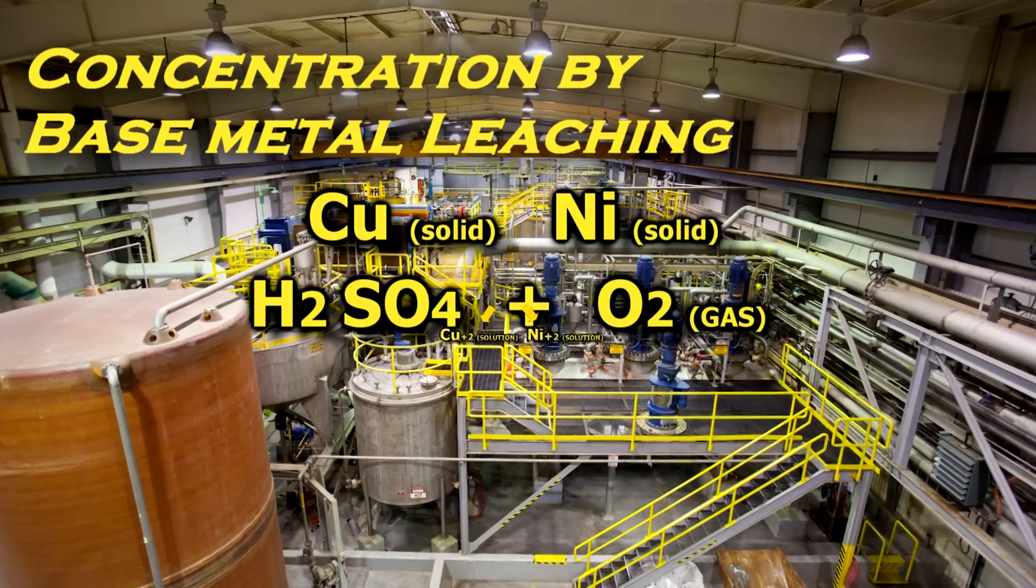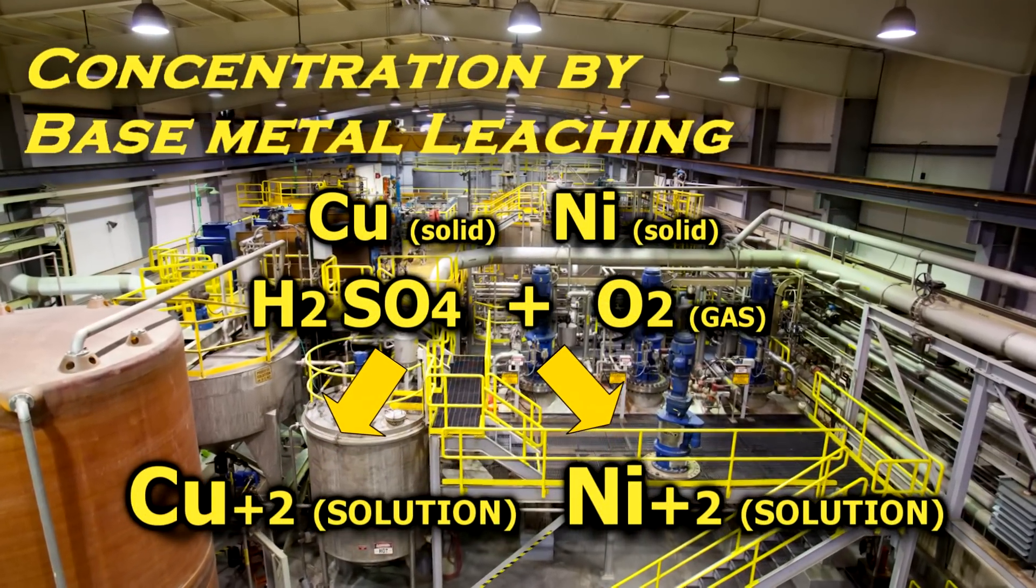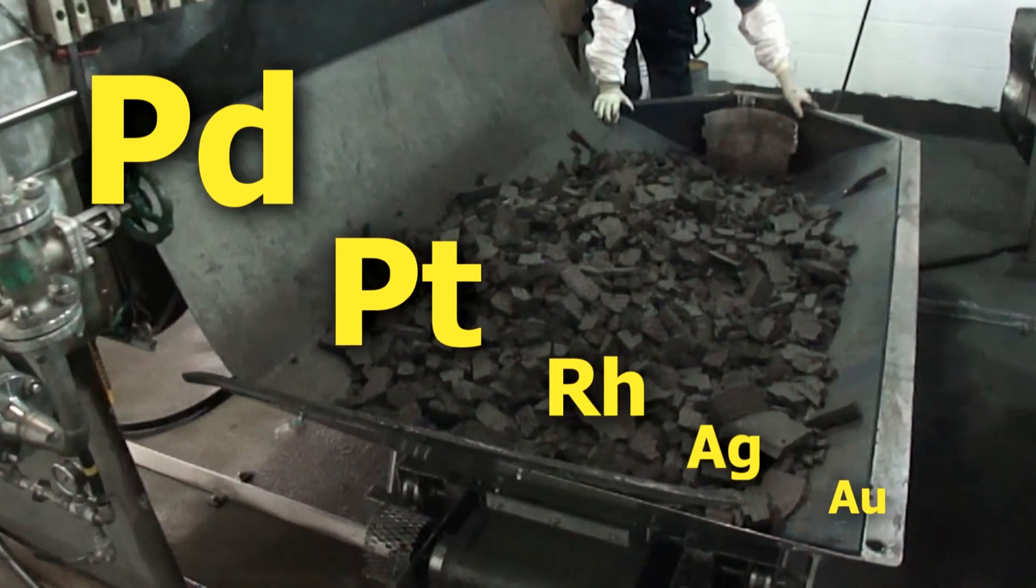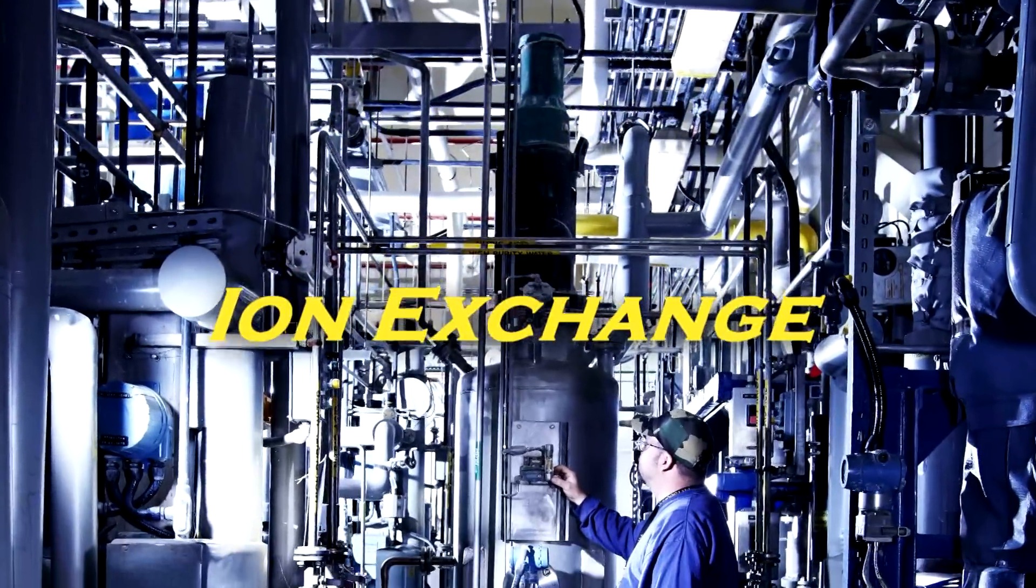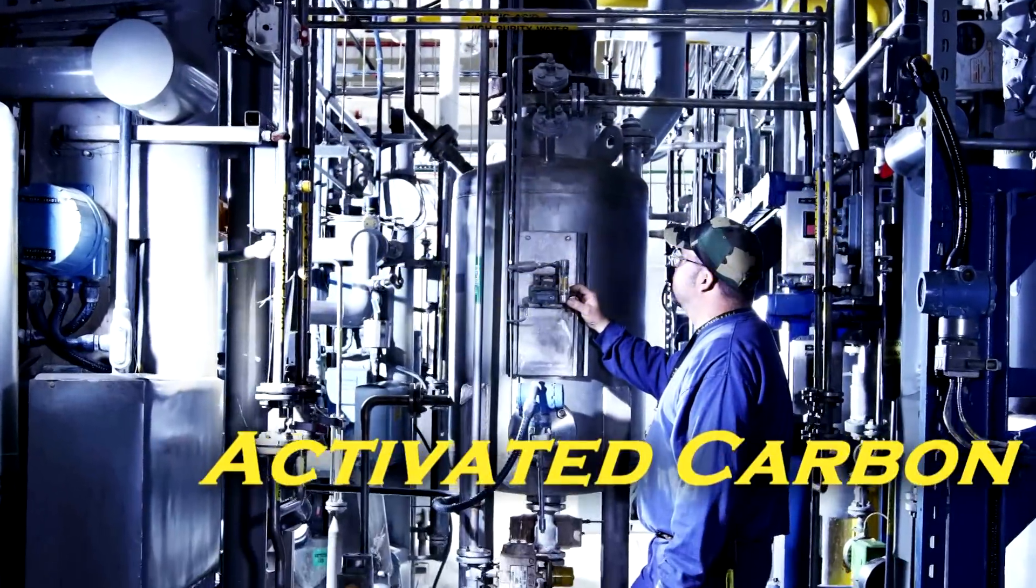Multi-stage, high temperature and pressure leaching is used to dissolve and remove these base metals using sulfuric acid and oxygen. The resulting solid material is filtered out and contains approximately 40% precious metal content. The other concentration methods use solvent extraction, ion exchange, and activated carbon.